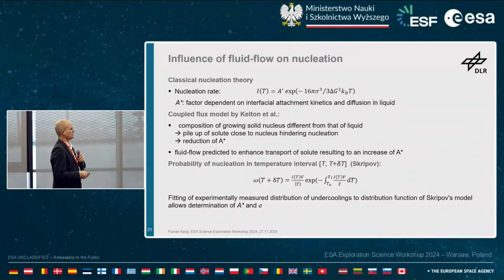So that's a quick glimpse into theory. You don't have to go through that in detail, but what I would like you to take away is, so you have classical nucleation theory. You can calculate the nucleation rate in this form, and there's this pre-exponential factor, and this depends on interfacial attachment kinetics and the diffusion in the liquid.